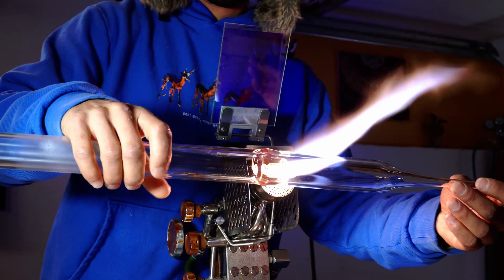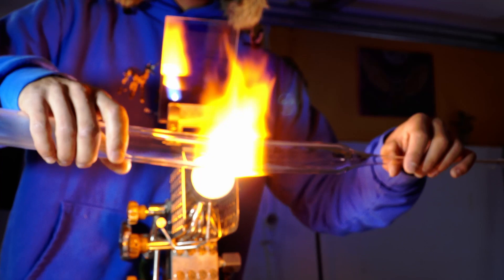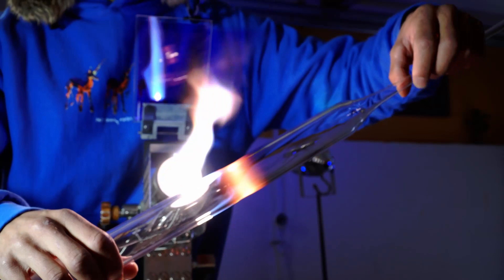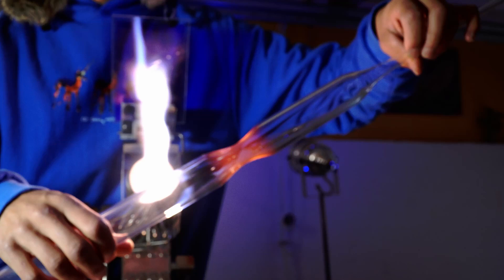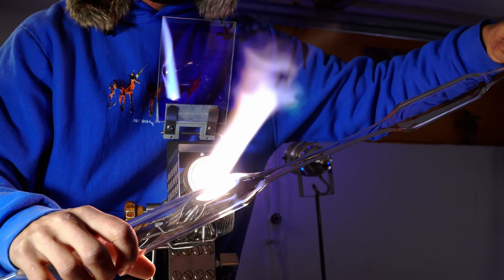We've got a good gather of glass inside of a tube. Now we're just going to heat that up so it's nice and evenly heated. And hang it down so gravity will carry part of it. At the beginning we're not pulling much. Just really letting that establish a wall weight. About twice what we ultimately want it to be. Now we're going to pull quite hard. You can see the tubing is quite even.